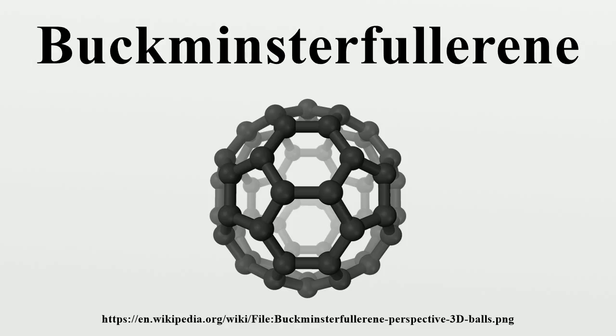Properties. Molecule. The structure of a Buckminsterfullerene is a truncated icosahedron with 60 vertices and 32 faces, with a carbon atom at the vertices of each polygon and a bond along each polygon edge. The van der Waals diameter of a C60 molecule is about 1.01 nanometers. The nucleus-to-nucleus diameter of a C60 molecule is about 0.71 nanometers. The C60 molecule has 2 bond lengths. The 6-to-6 ring bonds can be considered double bonds, and are shorter than the 6-to-5 bonds. Its average bond length is 0.14 nanometers. Each carbon atom in the structure is bonded covalently with 3 others.